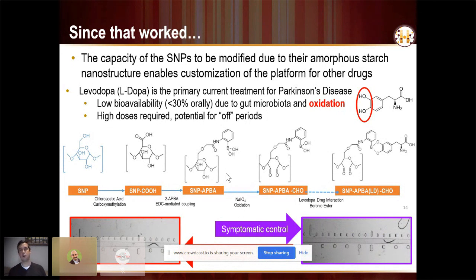In this case, levodopa is our target, which is the primary current treatment for Parkinson's disease. And it has very low bioavailability because there's a lot of degradation in the gut microbiota. It's also one of these catechol-like molecules, which have 2 hydroxyl groups adjacent to each other on an aromatic group, very susceptible to oxidation to quinones, which not only make the drug not work, but can also induce toxicity. So what we've been doing in this case is keeping the aldehydes so we can get the gel forming, but also introducing these phenylboronic acid groups, which are known to bind reversibly to cis-diol groups, such as those on L-DOPA, to stabilize them and also to control their release.